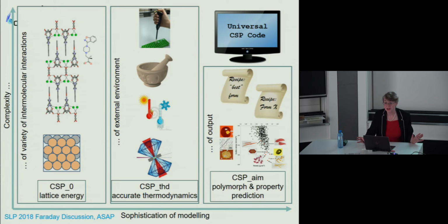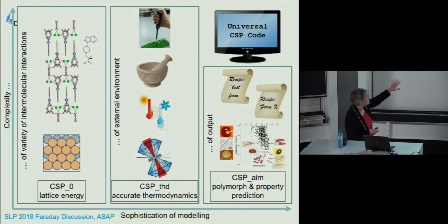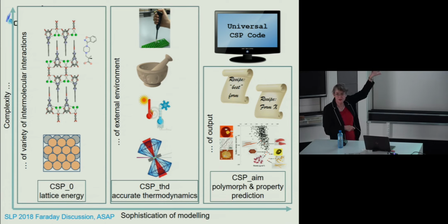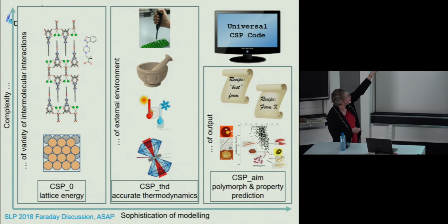So we've got a real challenge here of getting to what we want to get at from crystal structure prediction. Even at the 0th order, when we're dealing with lattice energy, there is a challenge of going up in increasing complexity of your system and the types of different inter- and intramolecular interactions you are trying to balance. That diagram is that drug molecule turned on its side. It's the chloride salt, and you've got layers where the layers can be bridged by different alcohols with the OH bonding to the chloride salt, and you have a nice van der Waals layer of the hydrocarbon chains.